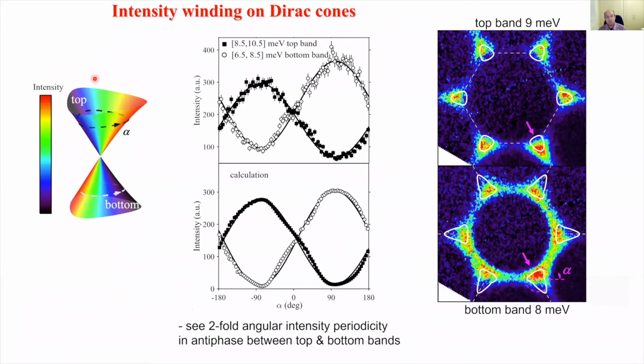And more quantitatively now, if we use the full J1, J6 model, actual positions of the cobalts and so on, this is the data, this is the calculation, looking at exactly the same azimuthal scans, same pixels. The maximum in the calculation is in the same position as in the data and so on. So there's very good agreement capturing this intensity modulation.